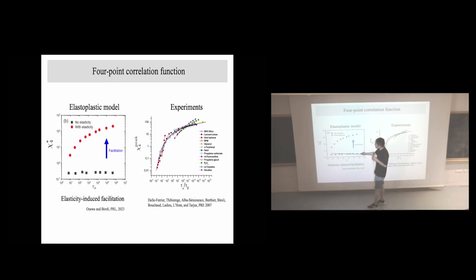First, we perform simulation for the model without elasticity. So no elasticity, just thermal activation. In that case, the Chi4 peak doesn't grow at all. Okay, no dynamical heterogeneity. But if you switch on elasticity, we see the growth of Chi4, growth of dynamical heterogeneity. So it means that at least within this simple model, the elasticity causes growing dynamical heterogeneity or facilitation.